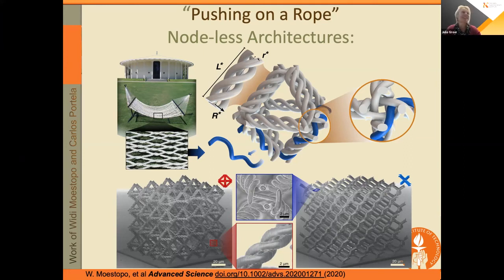Yes. What you're saying is music to my ears. That's exactly the holy grail, I think, because it's all about the separation of scales, right? Just like you're mentioning, at the characteristic material length scale, you have defects like point defects or dislocations or vacancies, et cetera. Now, when you zoom out effectively to the hundreds of nanometers, maybe there's collective dislocation cell wall formation, right? Or in amorphous materials, maybe there's collective void formation or something like that. And then when you architect it, now you're dealing with a separation of scale where it's more of a homogenized response.